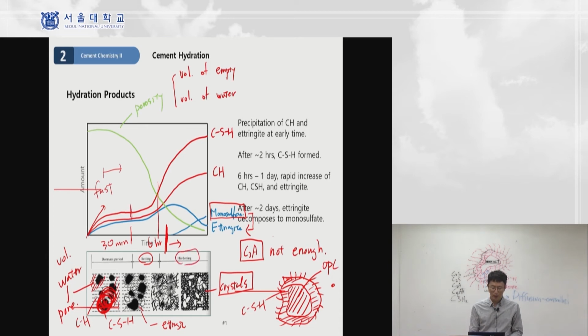Okay? So setting, we have a region here. The setting is important. For example, let's say we cast concrete to fill the foundation. Next we have to put more concrete to fill that void. But this next casting process should be done before the final setting time of the first cast. So setting has the initial set time, and also the final set time. So the next casting process should be done before the final setting time of the pre-existing concrete.